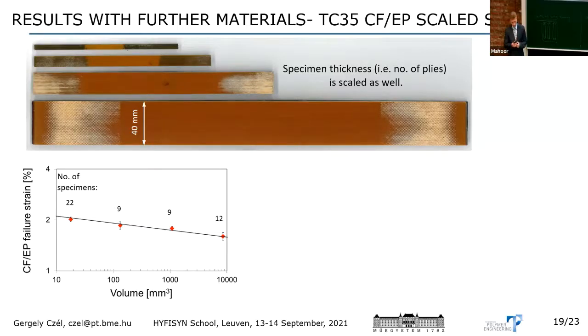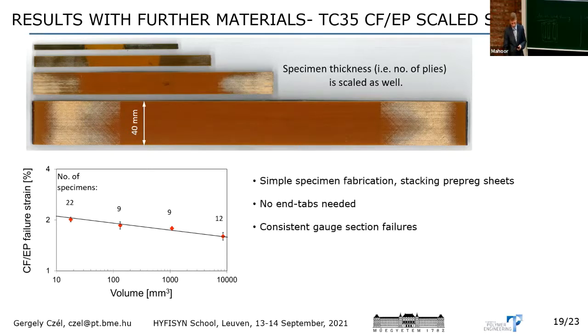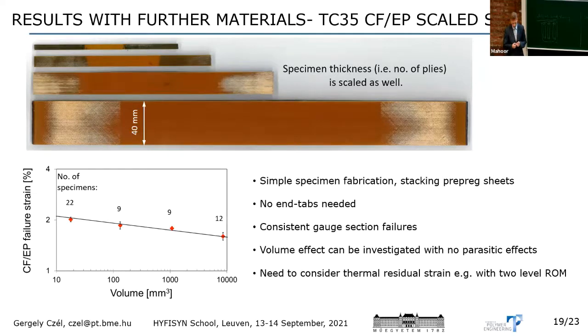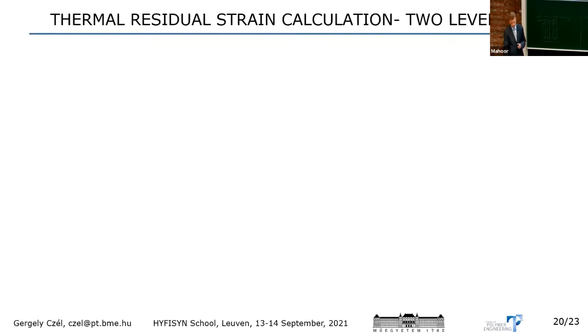So what else did we do with this technique? We did a scaled test study, because we realized that this way we can get rid of any parasitic effects, no stress concentration, nothing. So we can determine the real failure strain of different size, different volume specimens in an accurate way, and then it's possible to come up with a good Weibull modulus. But there is one issue: since we co-cure the layers at 130 degrees C, there are some thermal residual stresses arising in the specimen. So we need to consider this one.